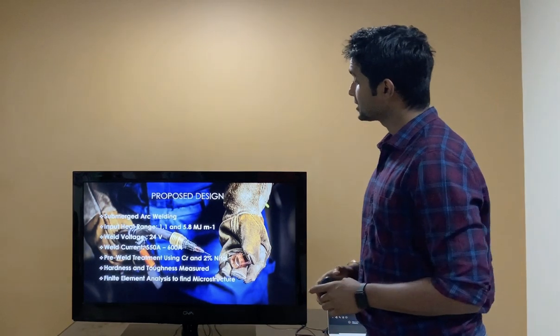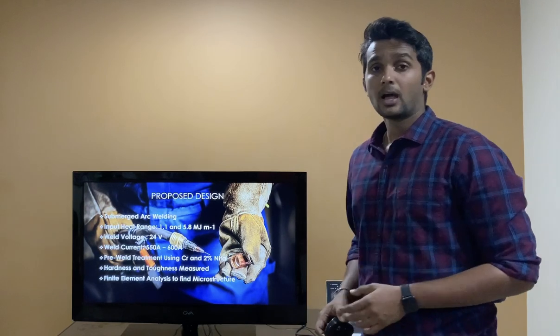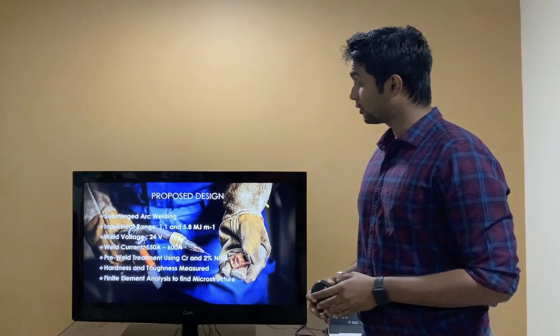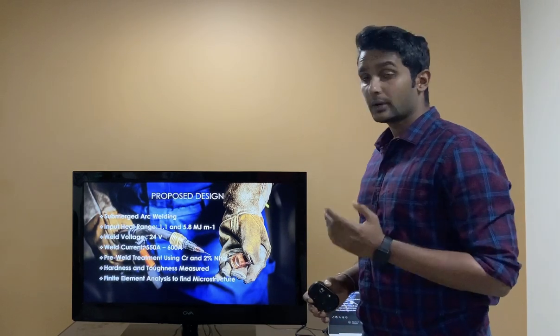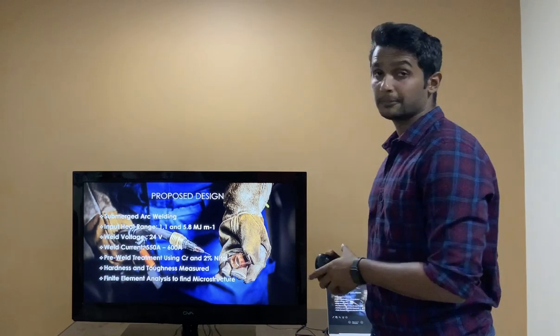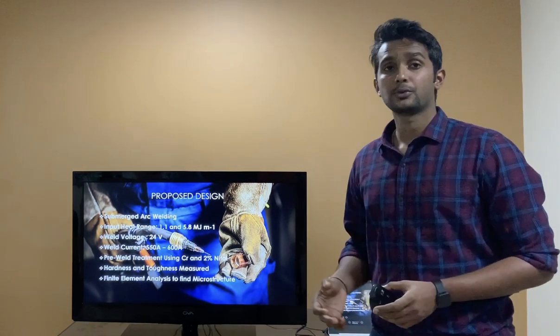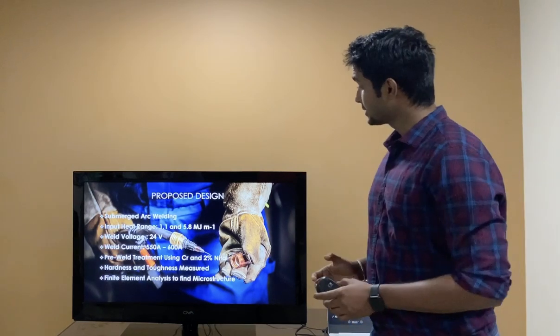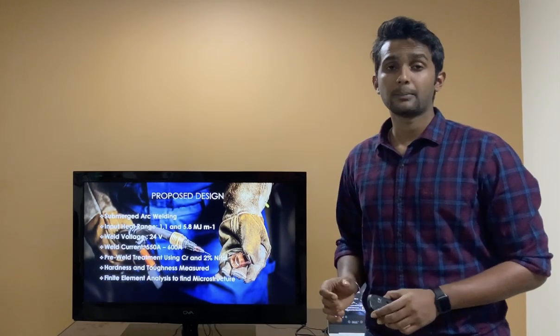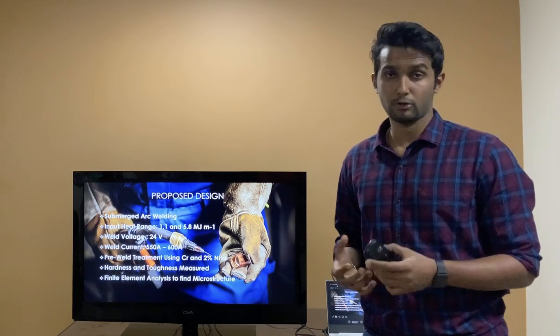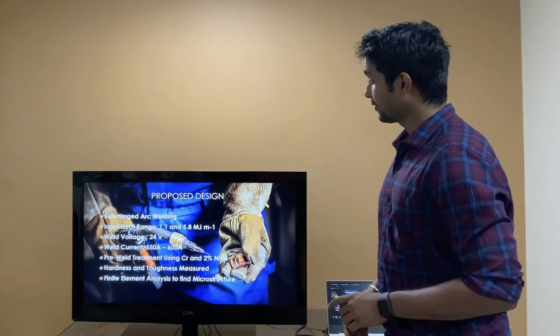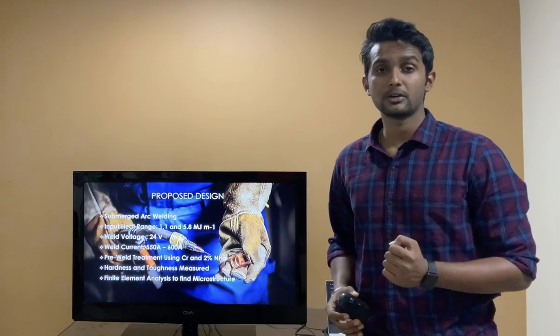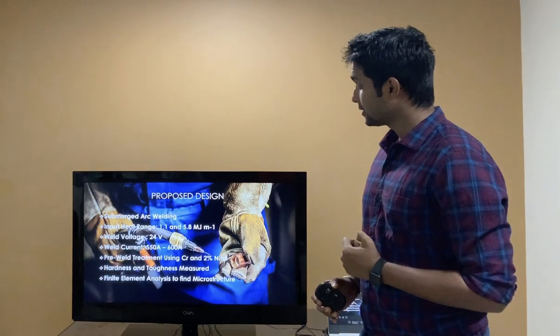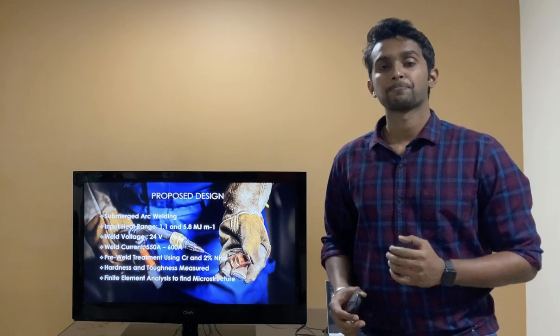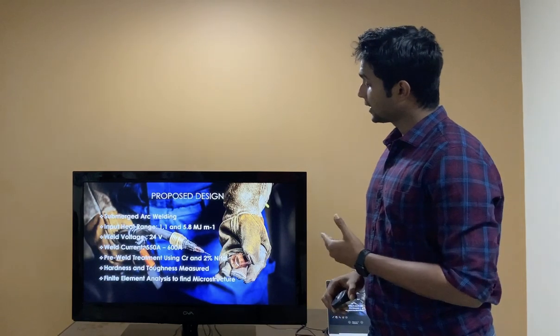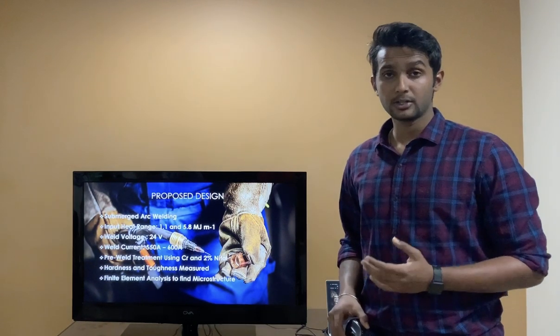So the heat input is in the range of 1.1 to 5.8, and the weld parameters are set to a weld voltage of 24 volts, and a weld current in the range of 550 ampere to 600 ampere as well. And the pre-weld treatment would be done to both metals using chromium as well as 2% of nickel, and this would prevent the weld joints from getting oxidized or corroded. And next comes the hardness and toughness. As I told earlier, hardness is measured using a Vickers hardness machine, and toughness gives you an idea about the strength of the weld joints. And the finite element analysis is done to find the uniformity of the microstructure.